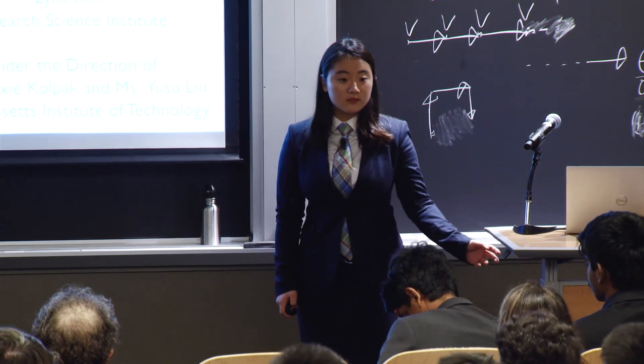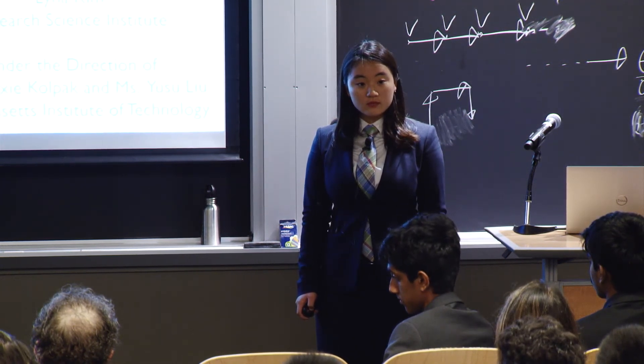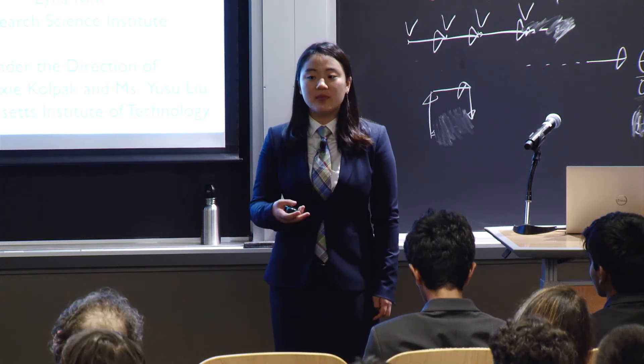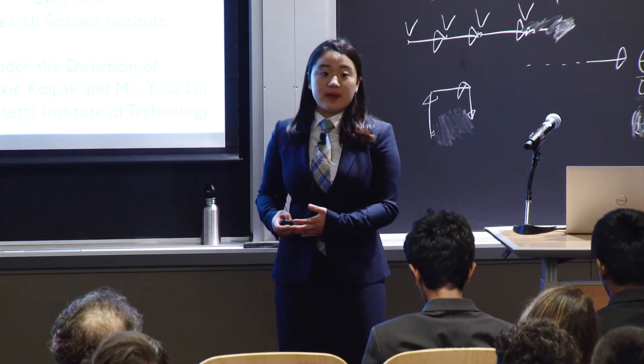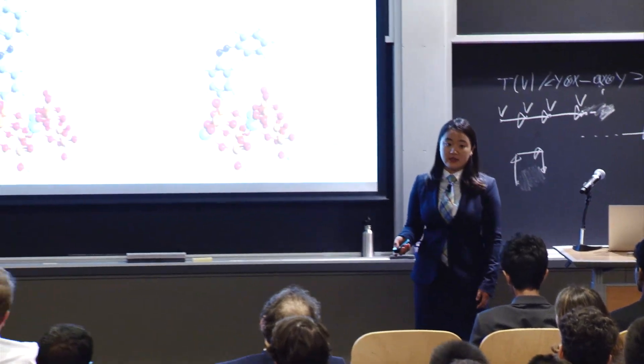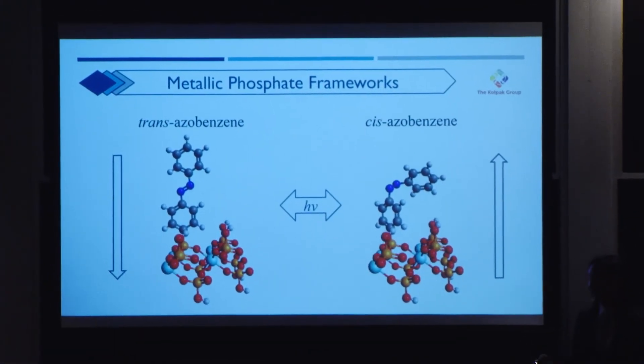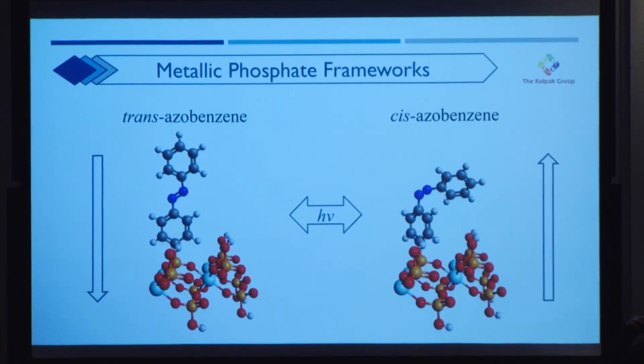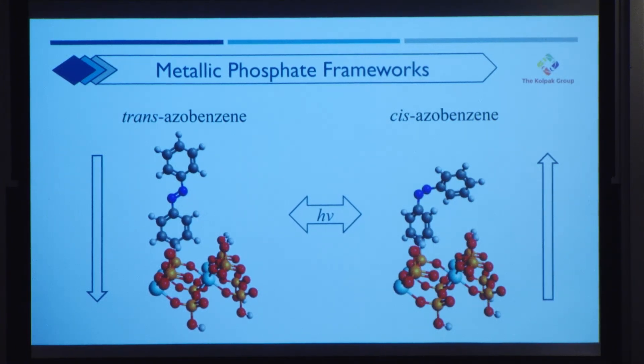Question: Why are the metallic frameworks able to increase the molecular energy density, considering that they don't participate in the energy storage cycle? How exactly do these frameworks increase the molecular energy density of azobenzene? They increase delta H in two directions. For trans-azobenzene, although the framework doesn't directly participate in the energy storage cycle, it stabilizes trans-azobenzene, which increases delta H downwards. For cis-azobenzene, because the framework allows you to pack azobenzene molecules more tightly together, you create steric clash between the molecules, which raises the energy of the cis-azobenzene upwards, also increasing delta H.